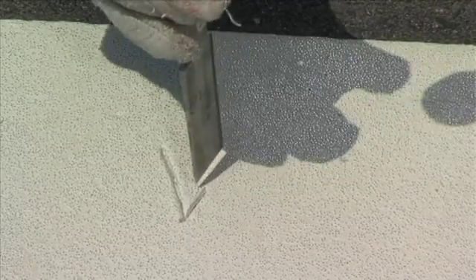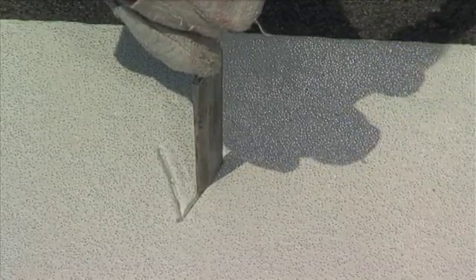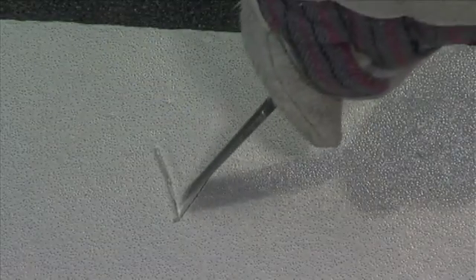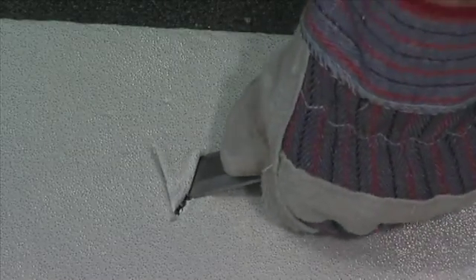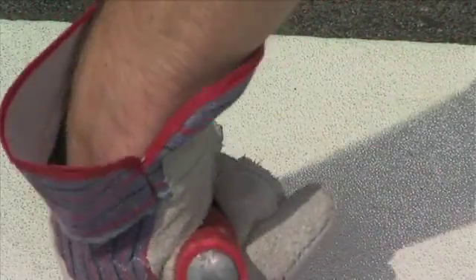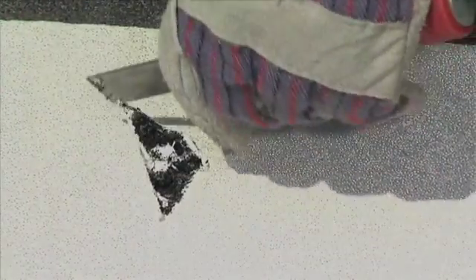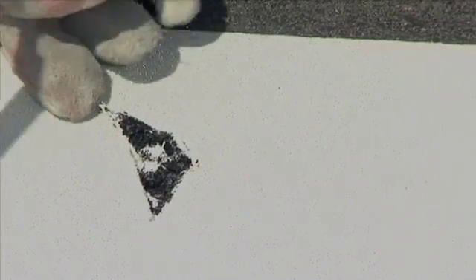Tap the chisel to create a small V in the material and pull back that piece to observe. If evidence of asphalt is on the underside of the material, sufficient heat has been applied. As you see here, a solid bond has occurred because aggregate is clearly evident on the underside of the material. Furthermore, the glass bead embedment is satisfactory as well. Next, we will do a chisel test for the preheat product on the right.